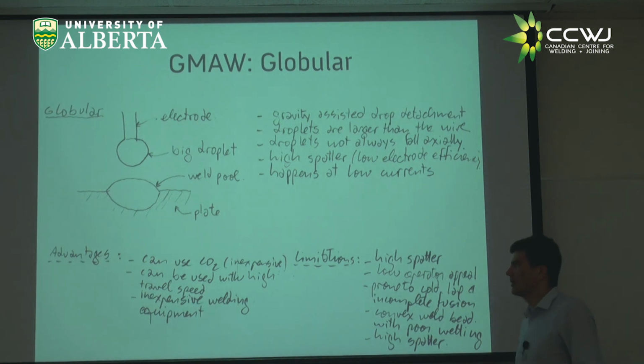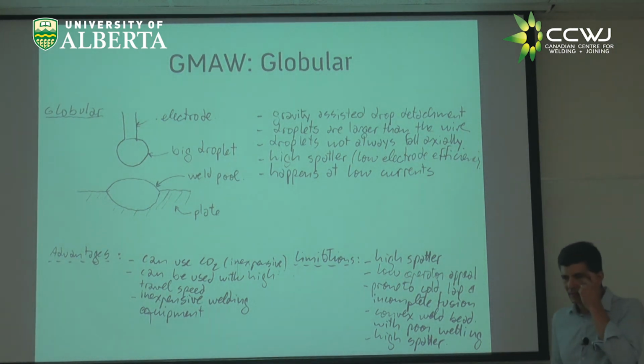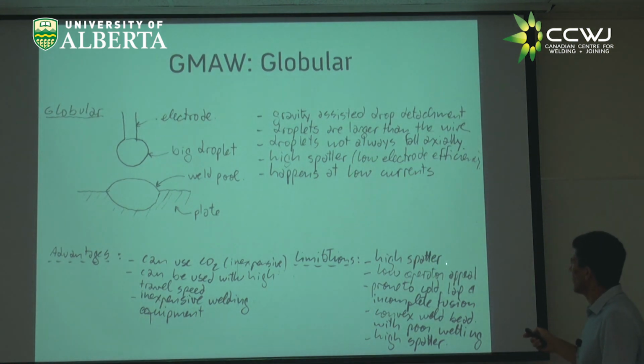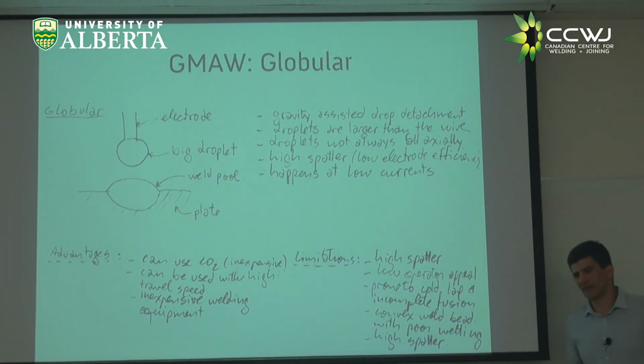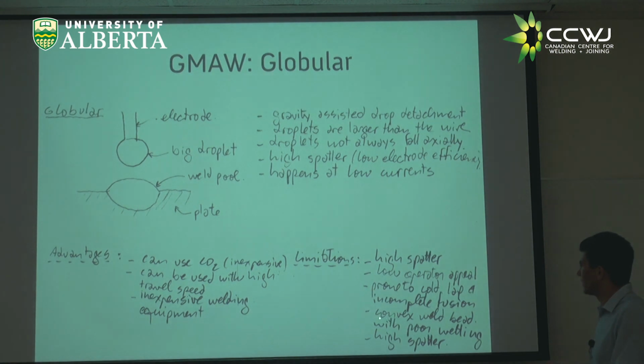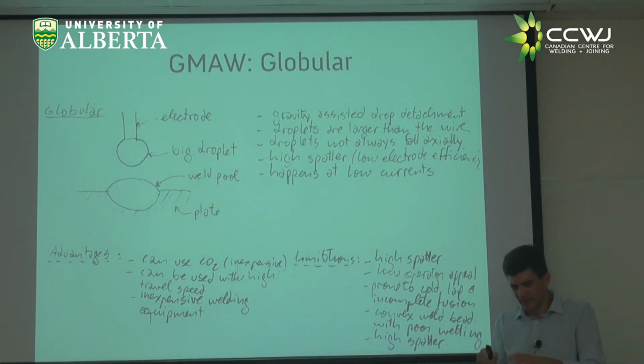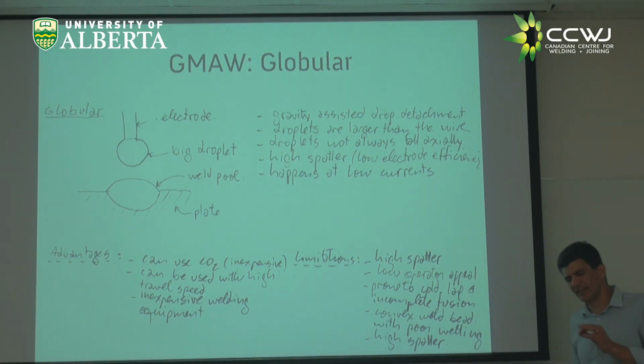The welding equipment in this case is relatively inexpensive, right? Because it's not a high quality metal transfer method. So these limitations, high spatter, operators don't like it, and very often if the welder doesn't like it, you know what, you have a problem. You end up with like a big weld bead, right? It's not as neat and clean as spray transfer.